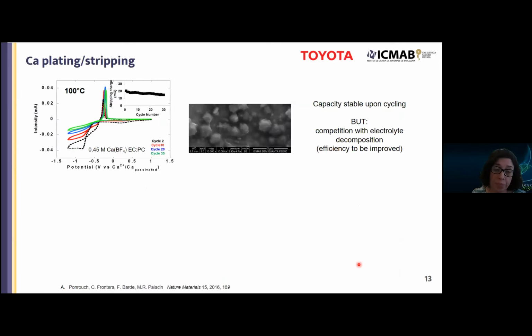And we realized that the issue was really formation of ion pairs within the electrolyte, and that just by simply increasing the temperature a little bit, using some specific electrolyte formulations, we were able to achieve plating and stripping. Here, the electrolyte is 0.45 molar calcium BF4 in EC:PC, and you see the cyclic voltammograms at 100 degrees C.